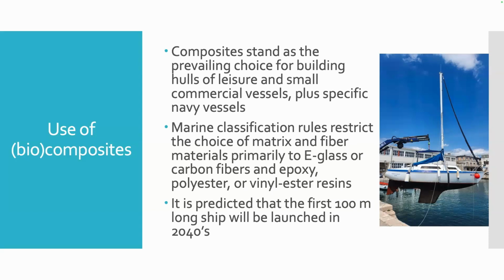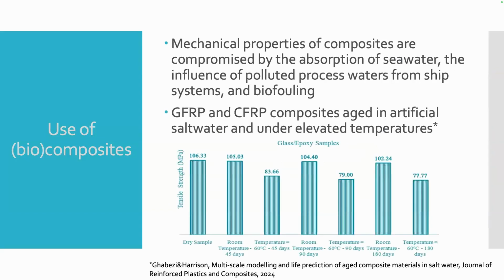And where is the problem? The problem is that we still don't know how they behave when they are in contact with the marine environment, meaning that the mechanical properties of composites are compromised by the absorption of seawater, the influence of polluted processed waters from ship systems, and biofouling. I have here presented the results of the study made by Ghabezi and Harrison that was published this year, who tried to see how well glass fiber and carbon fiber composites react when they are exposed to artificial salt water and when they are exposed to elevated temperatures.